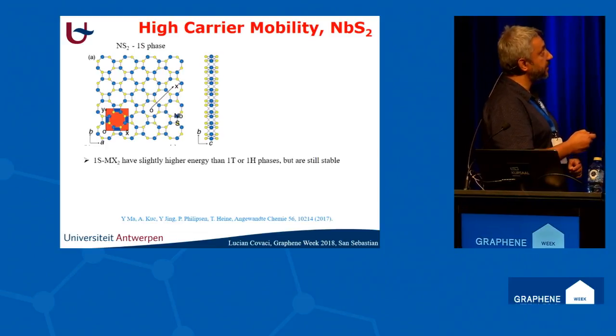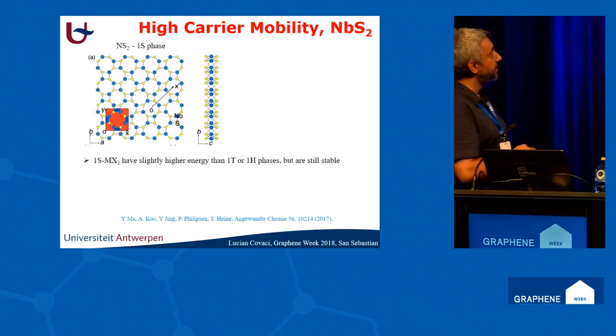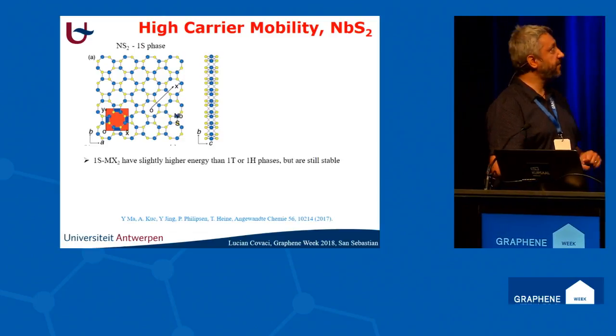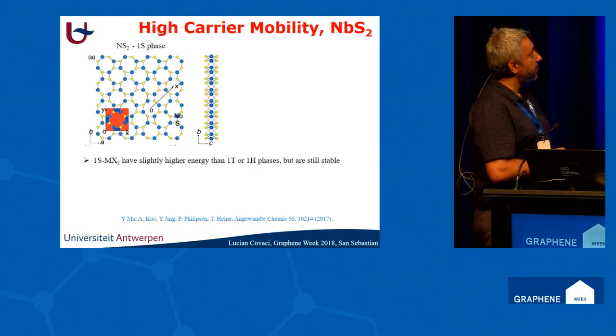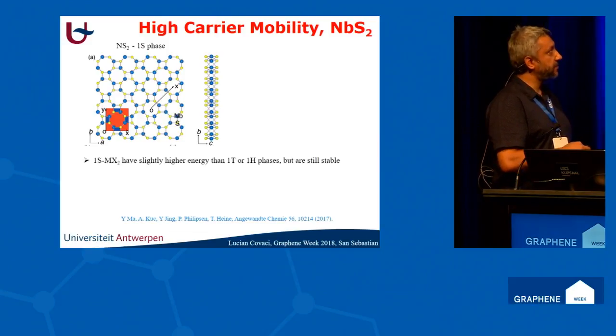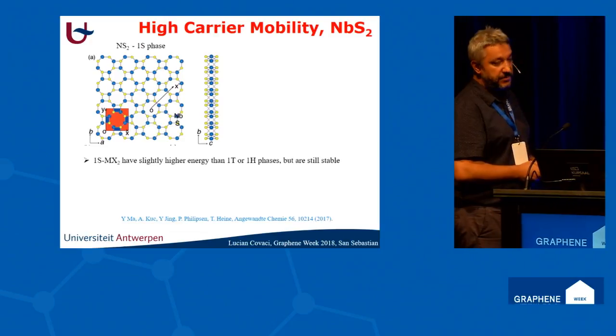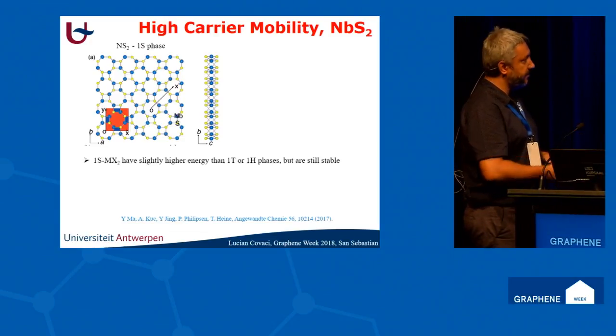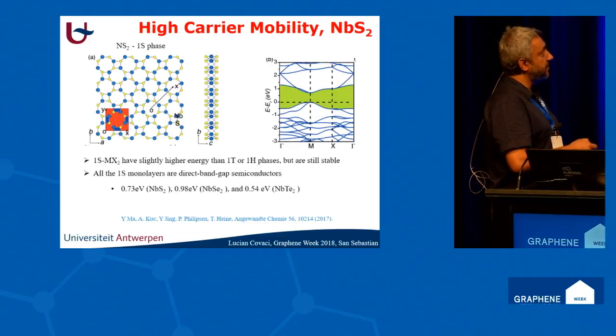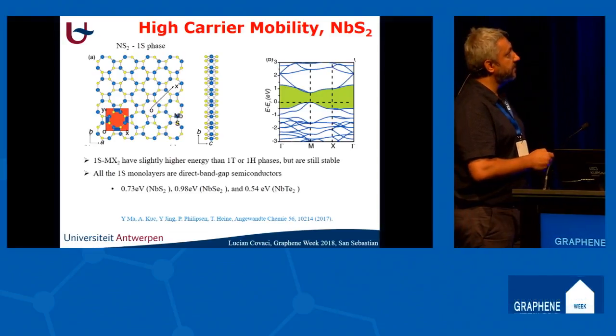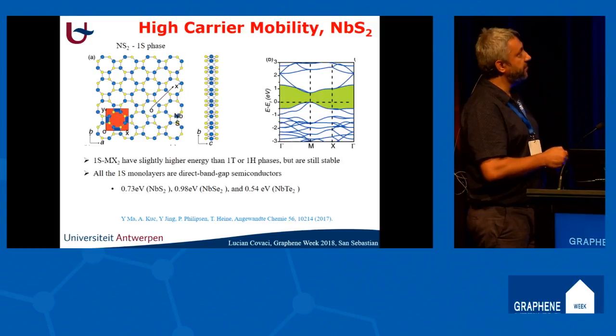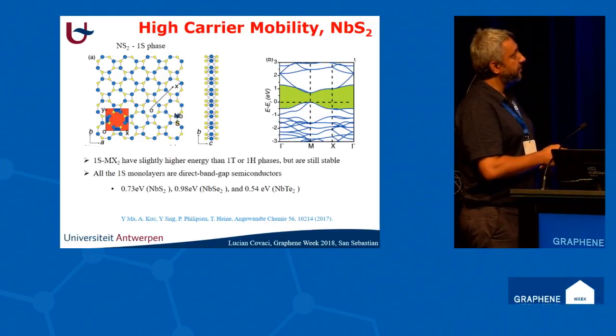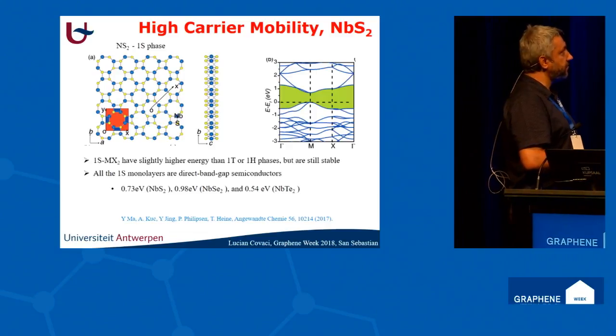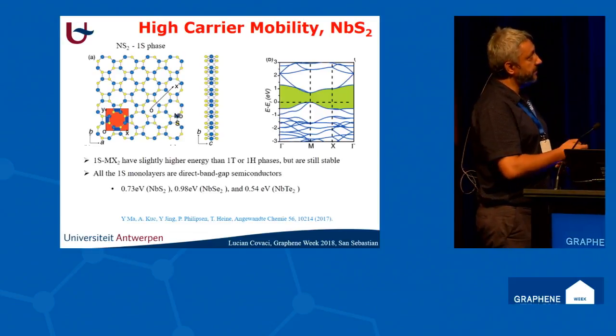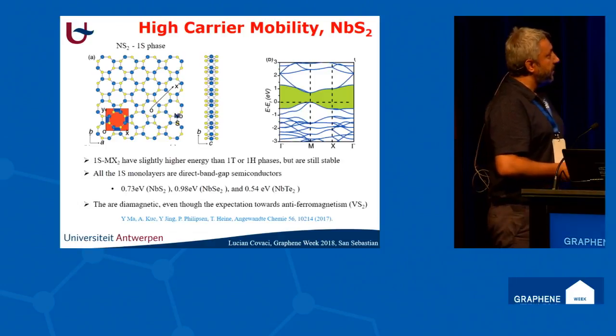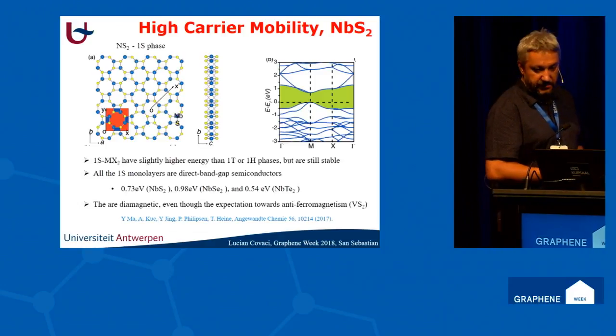Another such example is, again, a transition metal dichalcogenide, but the phase here is neither the H phase nor the T phase, but the so-called S phase, which actually has slightly higher energy than the T or H phases, but is still stable. So it's interesting to look at its properties, because one can maybe achieve these metastable states experimentally. We have shown that, again, this is very interesting for optical applications, because it has band gaps on the order of 0.5 to 1 electron volts. As you replace the chalcogen atom with sulfur, selenium, or tellurium, the gaps remain more or less of the same order. And I will just skip this point for now due to a lack of time.